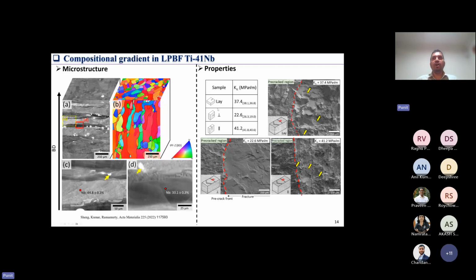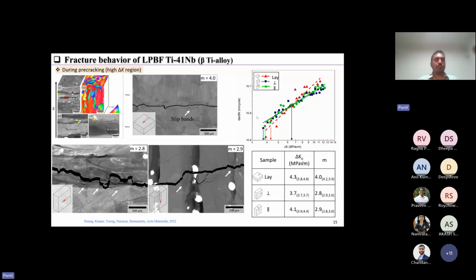And also, beta titanium alloys with omega precipitates usually show fracture toughness about this value, but because of compositional gradation, we are able to achieve almost double the fracture resistance we usually get in these omega precipitated beta titanium. And also during pre-cracking of this material, we see the same thing. When the crack goes through, it doesn't interact with niobium poor region. You can see very limited plasticity.